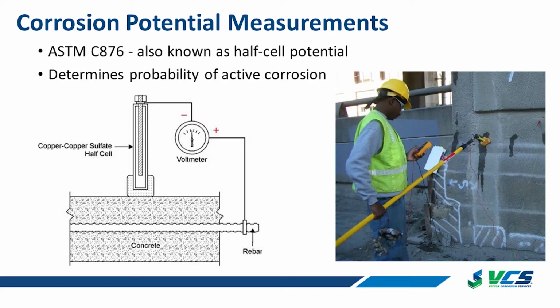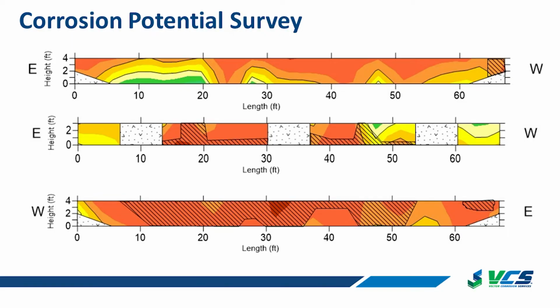So the white hatching there, you can see we've already gone and done a delamination survey. And by the way, this photo is not from that structure. It's a different structure, but just for example purposes. So, obviously you have where the concrete is delaminated, but you also want to know where the active corrosion is beyond the delaminations. And this happens to be, I believe, Pier 1, but indicative of what we were seeing on the structure as a whole.